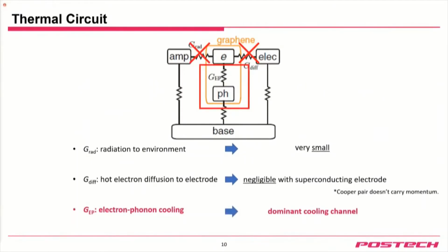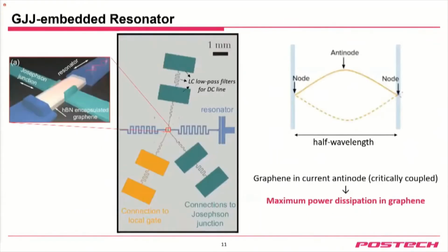So the only possible way for electrons to lose their energy is through the electron-phonon coupling. Energy transfers from the electrons to the phonons of the graphene, and this will be the dominant cooling channel. Okay, so this is our actual device. A graphene Josephson junction is inside this, and this is basically a half-wavelength resonator. When we input the microwave, this makes this kind of current distribution. The current oscillation amplitude is maximum at the center of this resonator, where we intentionally put our graphene, so that the graphene feels a large change of current, such that the ohmic dissipation is maximum. That's how we couple our microwave into the graphene.